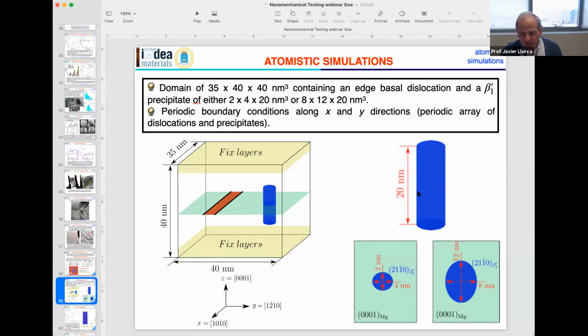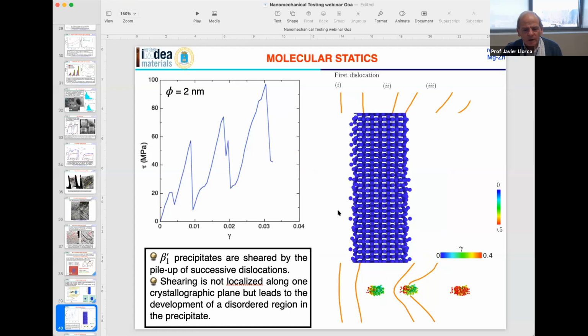Basically, we have 2 different types of precipitates. We have a small precipitate that is 2 by 4 nanometers in cross section, and we have a much larger precipitate that is similar to the experimental one. And what we do is we apply shear strain parallel to this layer and parallel to this layer, and then the dislocation moves and interacts with the precipitate. And this is basically what you get here.